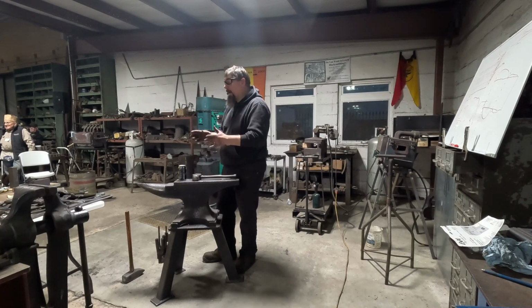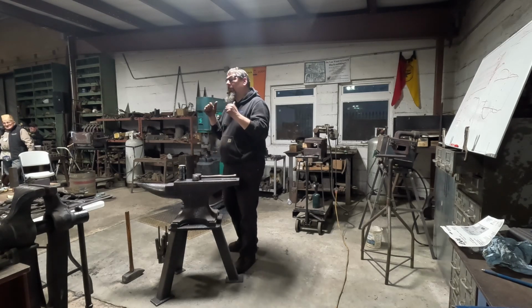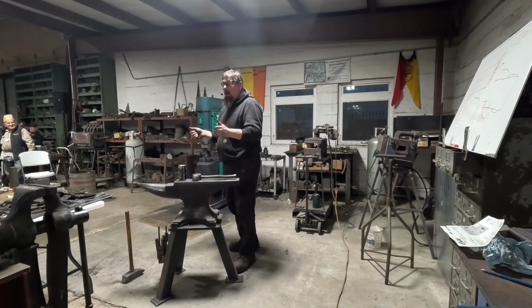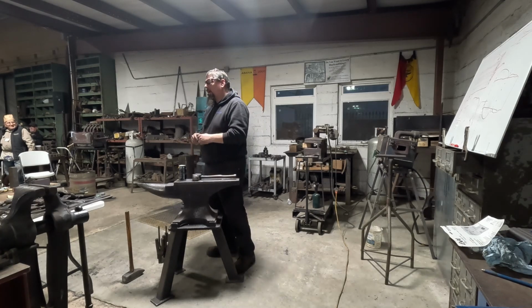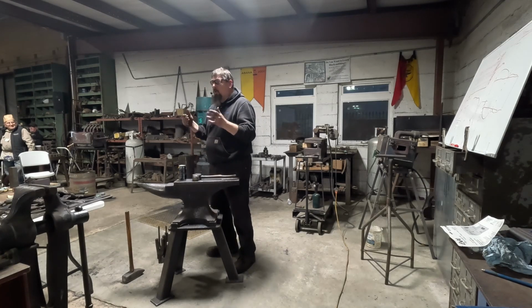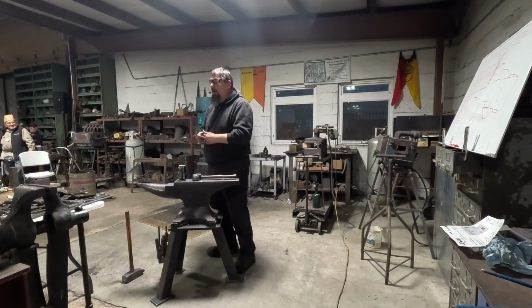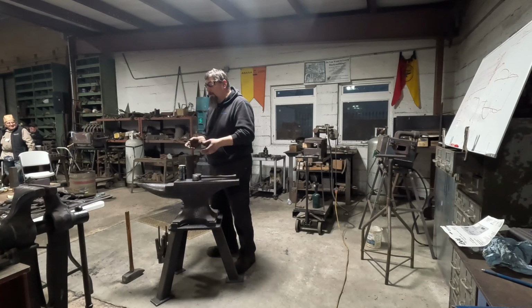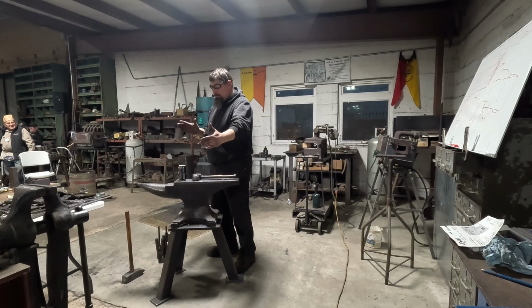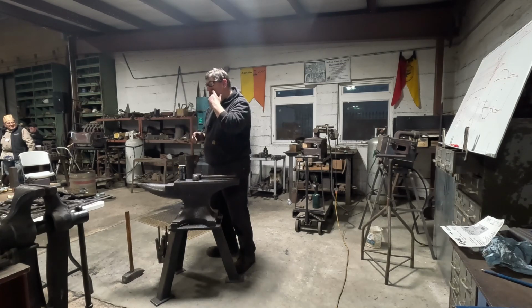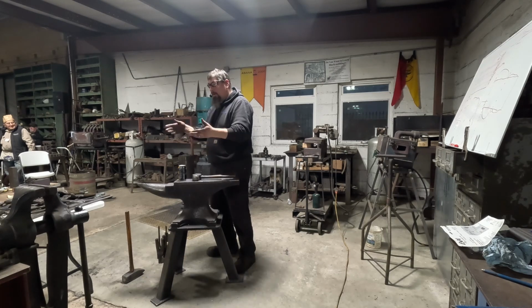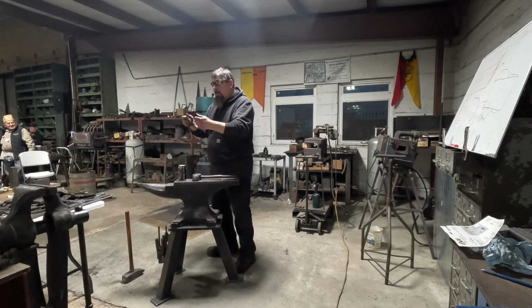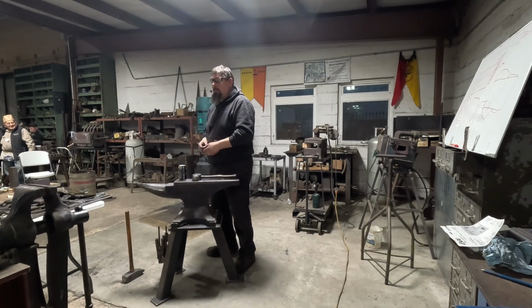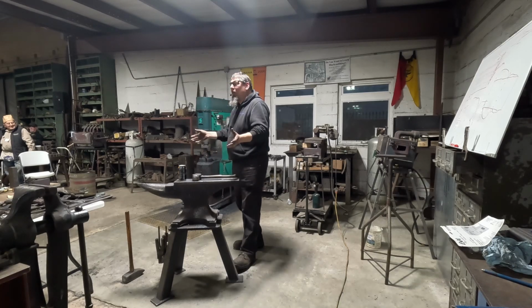Forge it at low temperature. Actually, the forge was fine at low temperature. So I'm like, okay, that's not wrought iron. Or at least if it's wrought iron, it's really good wrought iron. So I shouldn't have any trouble working it with just normal steel practices. So in the fire pit, pulled it out, and I had, I don't know, 18 inches of it hot or something like that. Went over to the power hammer, had some tooling available to control size, just like we were doing here. Thump, thump, thump, pieces started falling off the bar. Completely falling on the floor.